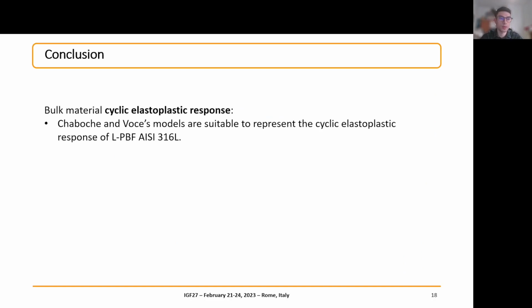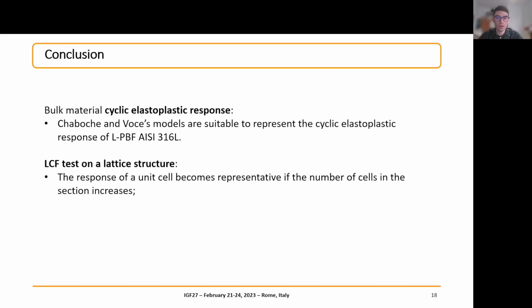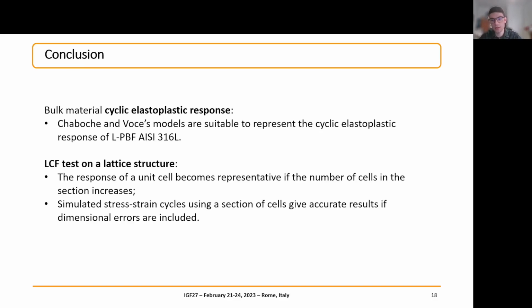So now I conclude my presentation with a summary. We can say that Chaboche and Voce models are suitable to represent the cyclic elastoplastic response of the bulk material and the lattice structure. Concerning the low cycle fatigue test on the lattice structure, the response of the unit cell becomes representative, increasing the number of cells in the section. And then the best results are obtained if we also include the dimensional errors in the finite element model.